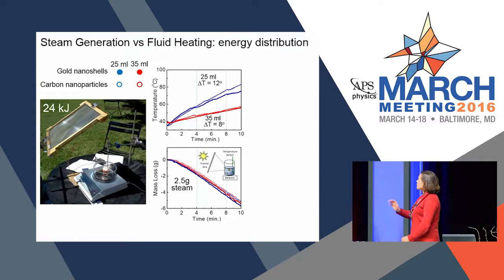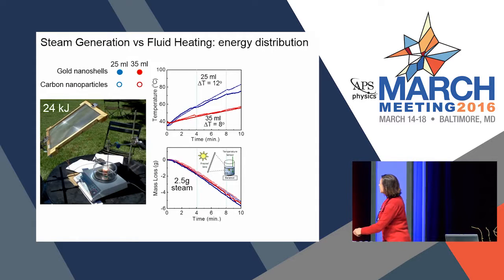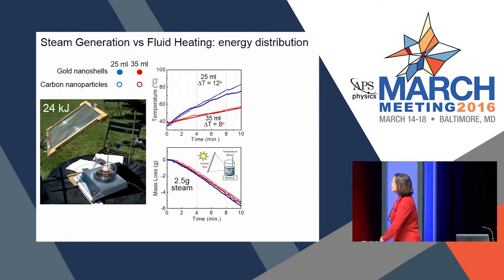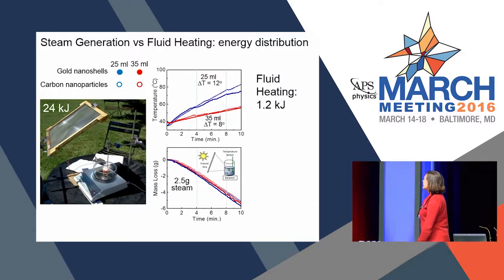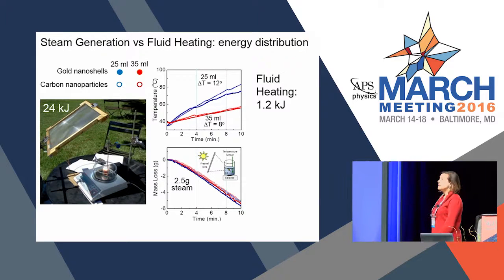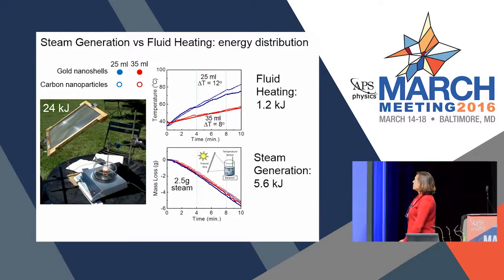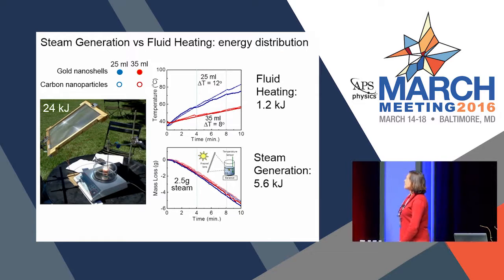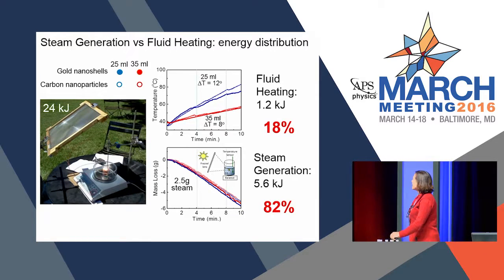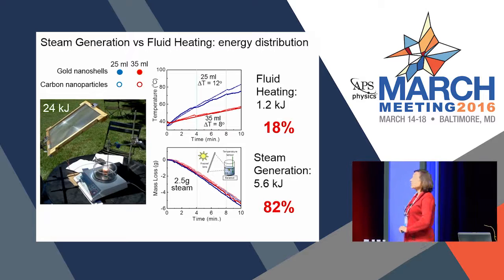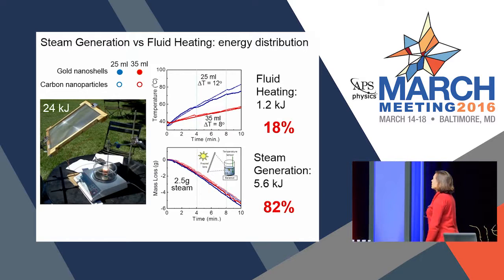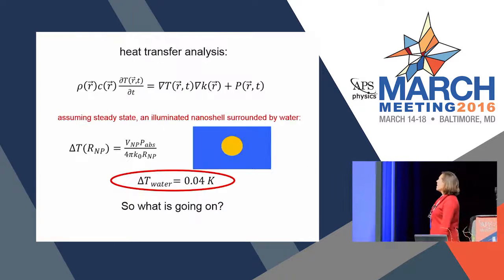And if we just measure, say, in this 4-minute window between 4 and 8 minutes, then what we find is that the amount of energy used to heat the fluid and the amount of energy used to generate steam are quite different. And so about 80% of the total incident energy goes directly into steam production and not into fluid heating. So what could be going on here?